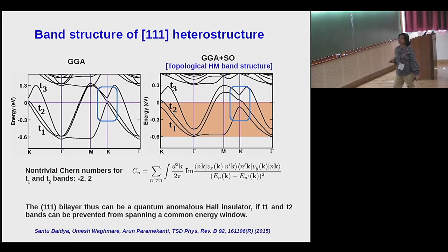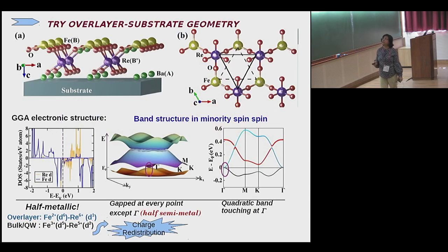We can make it insulating if we somehow can make these bands move far from each other, and that is possible if you can enhance the crystal field splitting between these bands. So in the next stage, what we basically considered is an overlayer substrate geometry.